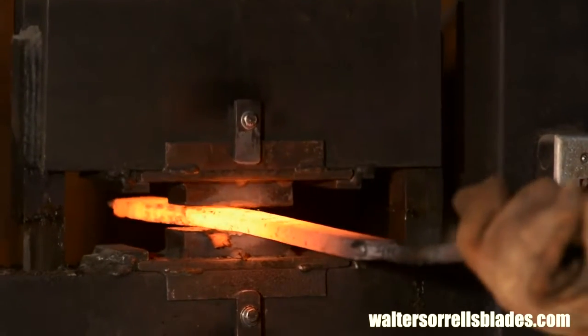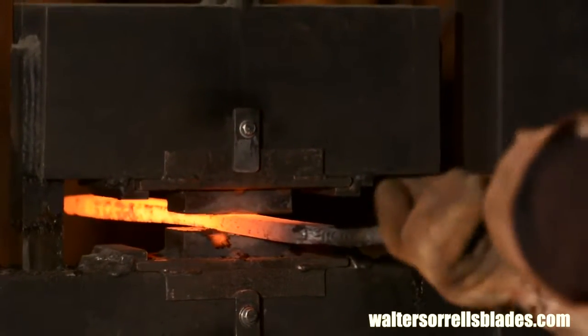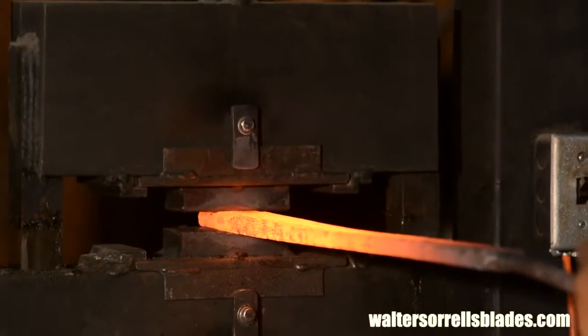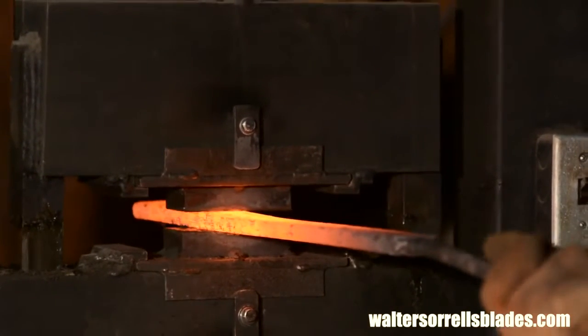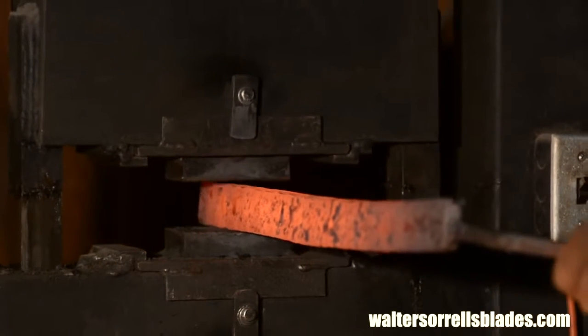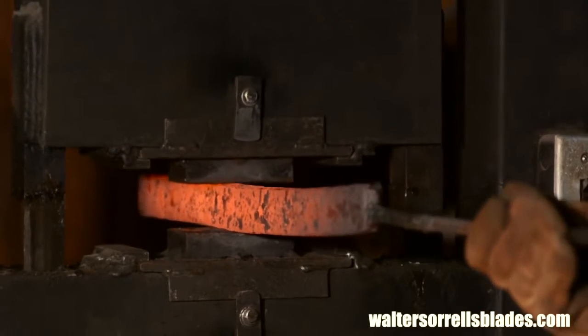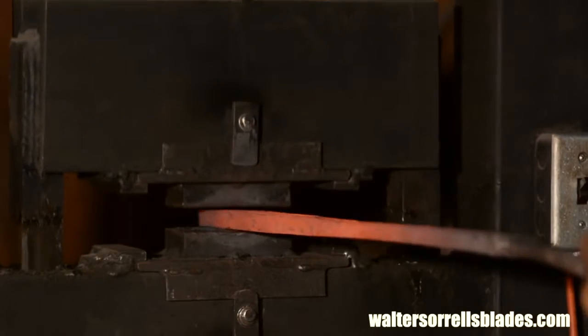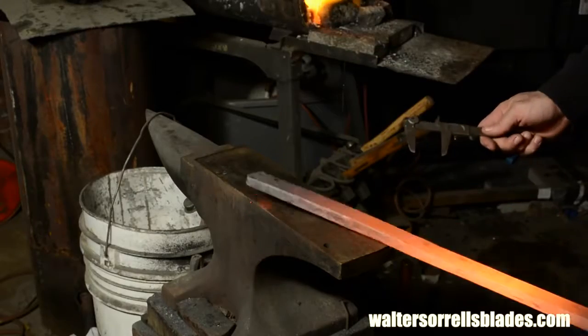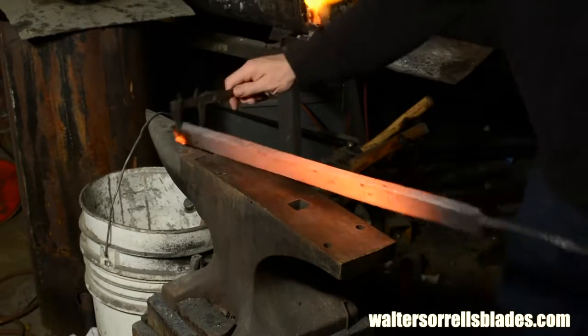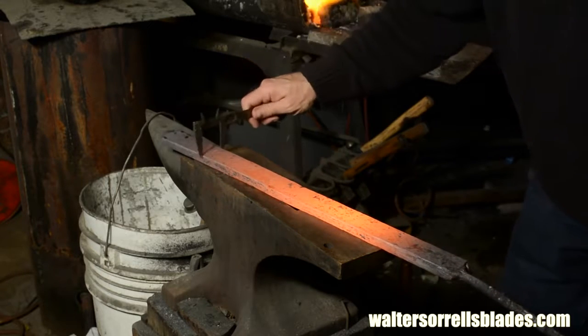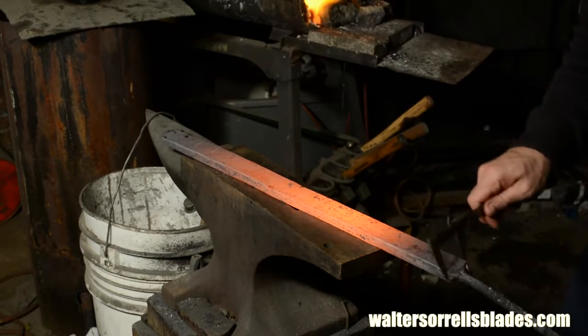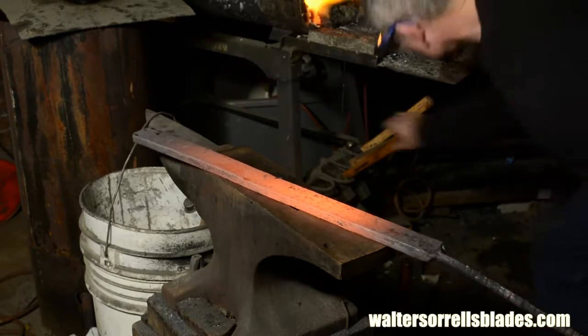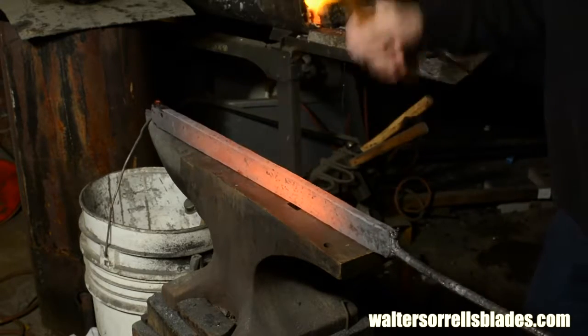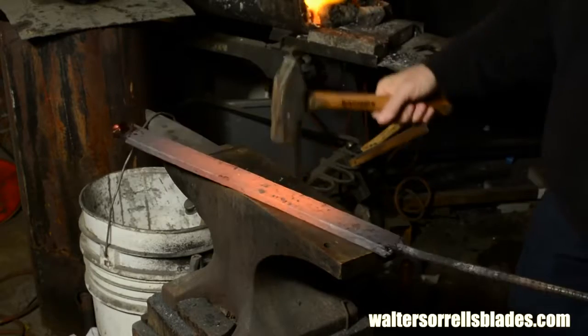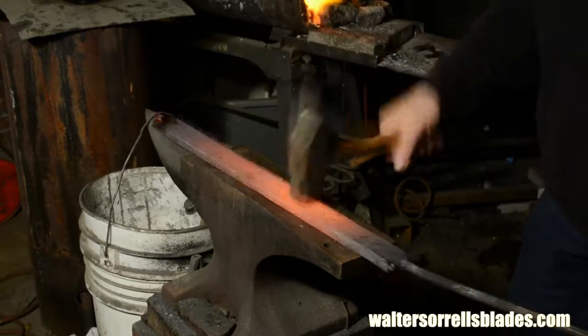I usually go about 1 3/4 inches to 2 inches wide and about 15 to 18 inches long. That just happens to be a comfortable length for drawing out the size billets that I make. Nothing particularly magical about those numbers. The most important point is that I want the width as even as possible. So, I'll measure it with these rusty old calipers. The point is not that it be 1.937 inches wide or whatever, but that it be a relatively consistent width from end to end. You'll see why in just a minute.